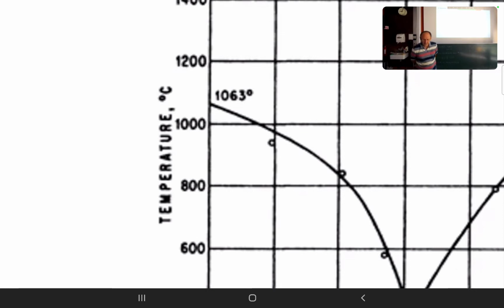And that means we could think about a die attachment process for silicon, because most silicon chips we have, they tolerate temperatures of 400 degrees centigrade for a short time. So it normally will not damage them. Many processes in silicon processing are significantly higher. Of course, for the aluminum metallization, we should not go to higher temperatures for longer times. That would not be good, but yeah, such many chips tolerate that a little above 400 degrees centigrade, if it's only for a few seconds. Because then the time is too short for significant diffusion.